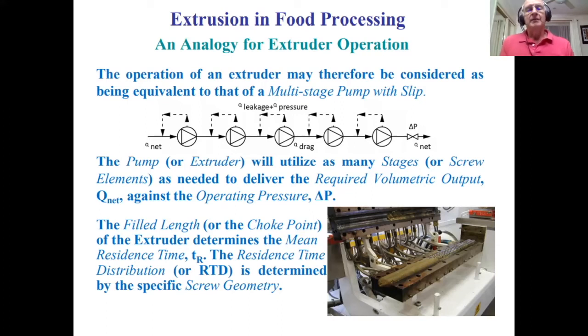And this ends up controlling the filled length of the machine that defines the average residence time within the extrusion cooker. And then it's the residence time distribution, which we can influence by the specific screw geometry, that influences the final cooking characteristics of the material. Now, for most extrusion processes, the average residence time is quite short, usually less than 1 minute. So this cooking process of starches and proteins that Gordon described earlier normally takes a significant amount of time, and the extruder does it in less than a minute typically. So clearly the processes and the chemistry and physics involved are different. And this is why we like to stress that extrusion is all about cooking, but it is not gelatinization, nor is it denaturation. It's something else.